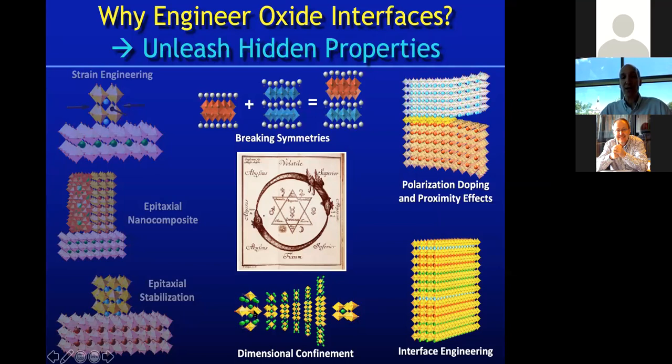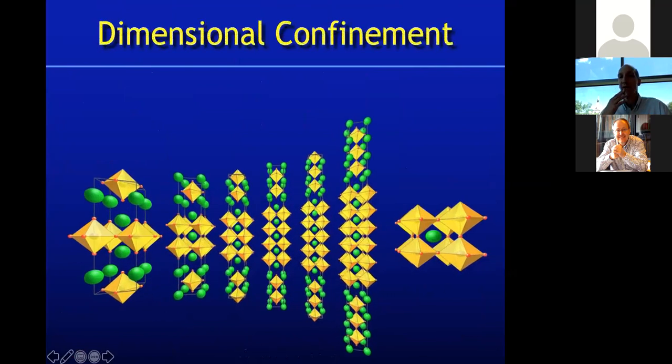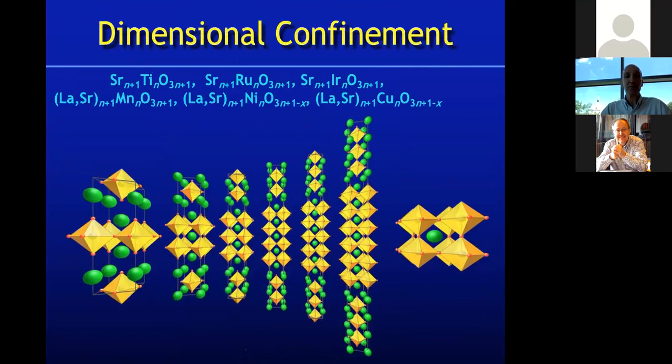So it's got one of the perovskite layers, but then two of the rock salt layers, whereas a perovskite has one of the perovskite layers and one of the rock salts. So it's like a one-to-one superlattice of TiO2 and strontium oxide, whereas here it would be TiO2, strontium oxide, TiO2. So let's look at this from a synthesis perspective in thin films. The structures are named after the original inventors. So Ruddlesden and Popper discovered the first three members of this series, and that's all that has been made in bulk in single phase form in the strontium titanate system.